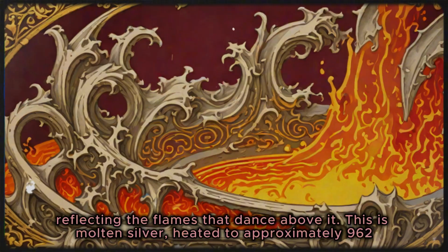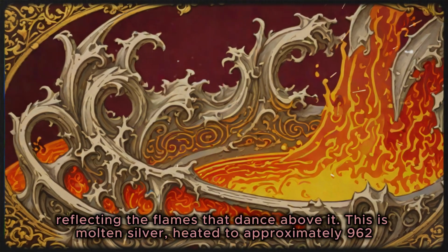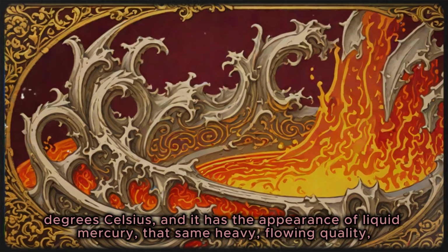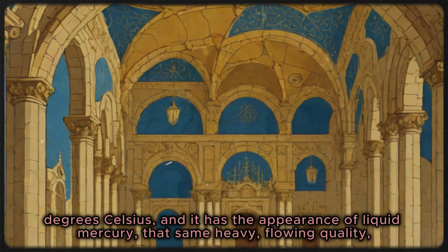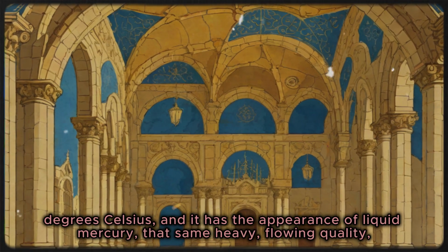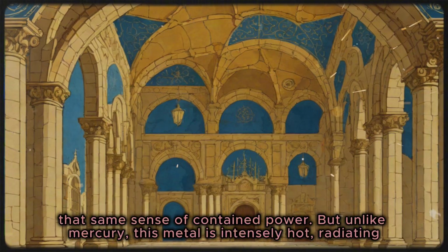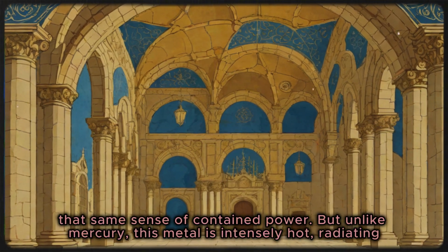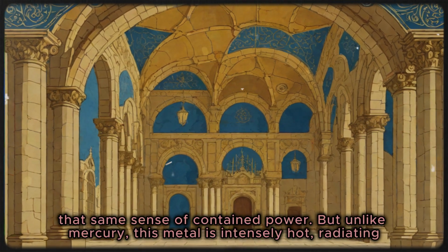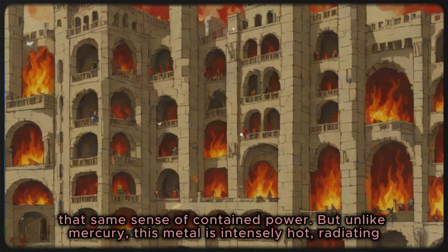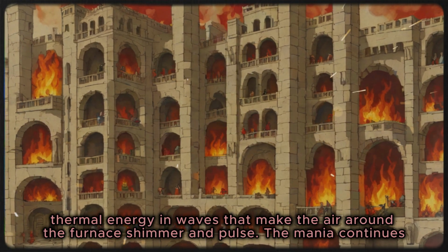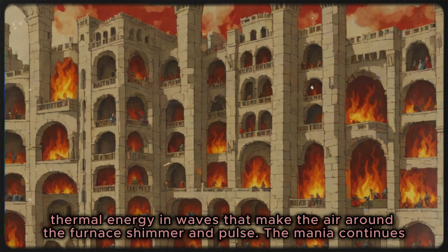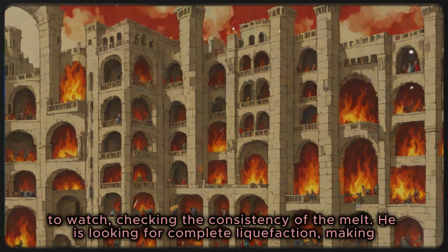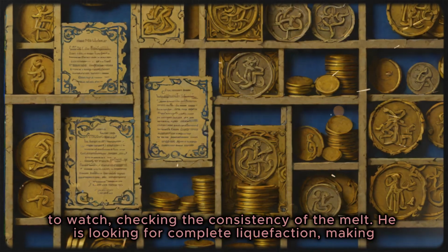This is molten silver, heated to approximately 962 degrees Celsius, and it has the appearance of liquid mercury, that same heavy, flowing quality, that same sense of contained power. But unlike mercury, this metal is intensely hot, radiating thermal energy in waves that make the air around the furnace shimmer and pulse. The moneyer continues to watch, checking the consistency of the melt.